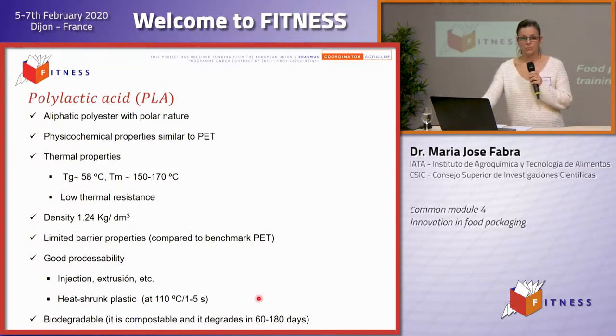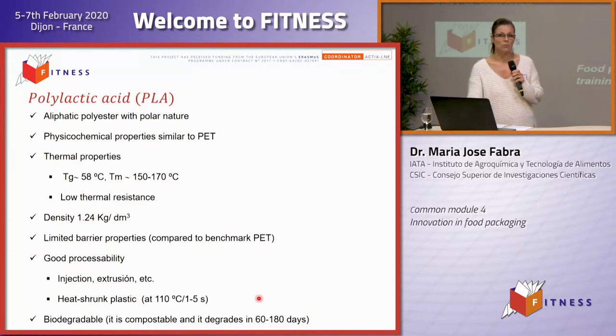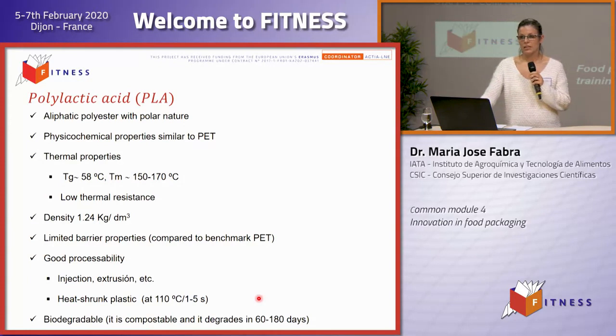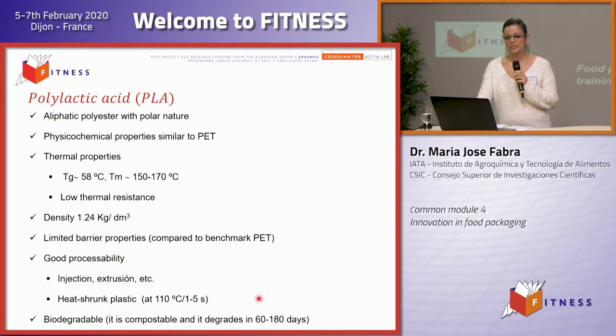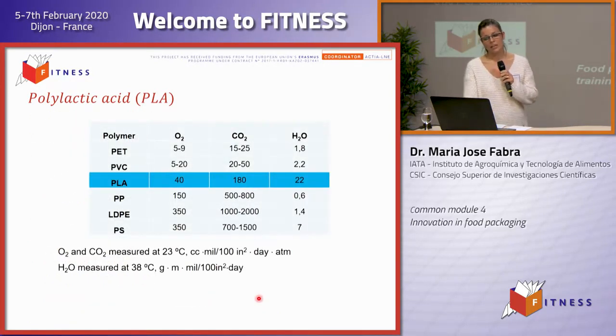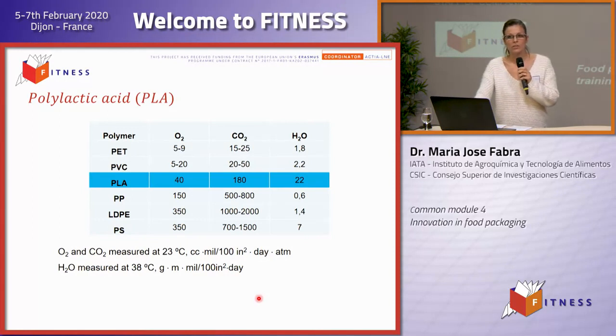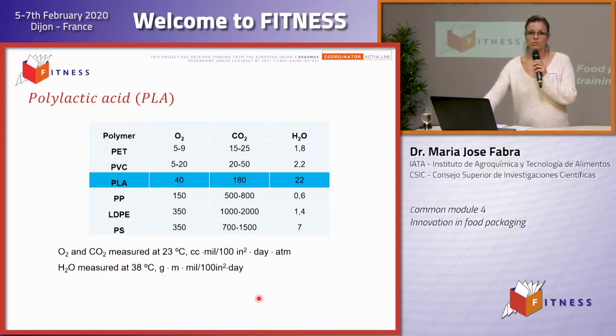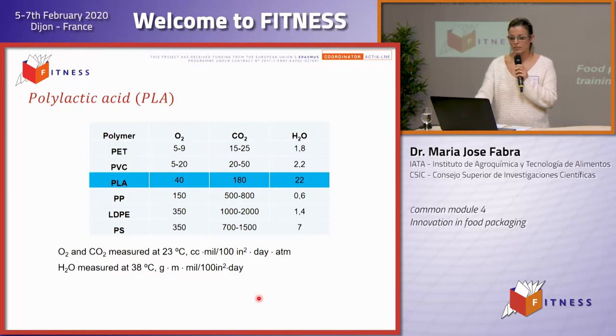And this PLA has limited barrier properties compared to the benchmark PET. However, it can be processed by the conventional equipment used for petro-based materials, the traditional packaging materials, such as injection and extrusion. And this material is biodegradable, it is compostable, and it degrades in between 60 and 180 days. Here are the oxygen, carbon dioxide, and water barrier properties of PLA compared to other synthetic materials. As you can clearly observe, barrier properties are lower than the synthetic materials. However, this can be used as a positive point to develop active biopolymers for food packaging, as I will explain to you later.